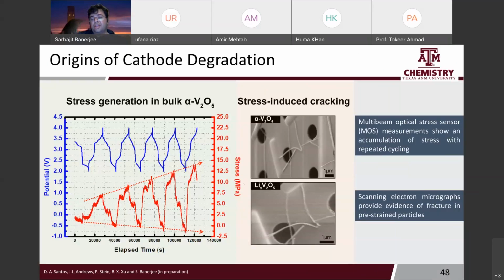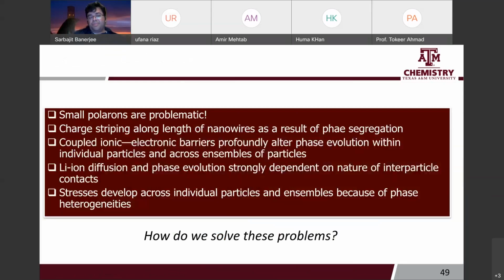It fractures, again, showing the role of this intercalation-induced phase transformations and phase separations, especially in curved regions and particle curvature regions where you can have an accumulation of stress that results ultimately in plastic deformation. So, this is a major origin of cathode degradation. So I think, again, the lesson for students, perhaps, it's important to keep in mind that we not only have to worry about chemistry, but we also have to worry about mechanics and the coupling between the two, right?